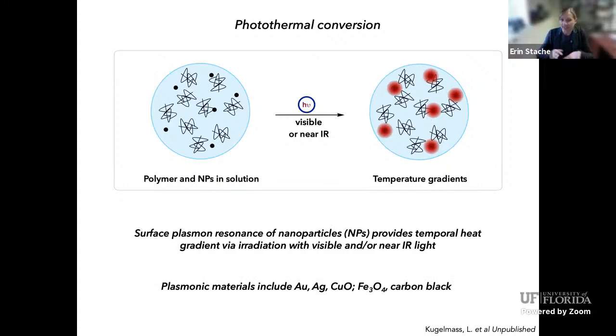The way this works for many of these nanoparticles is through surface plasmon resonance of metallic nanoparticles. These are things like gold and silver and copper oxide. What happens is you get a collective oscillation of the conduction band electrons when they get photoexcited. These are in resonance with the incident wavelength of light, and this creates a very large cross-sectional absorbance, which then when it relaxes back down, gives off heat.